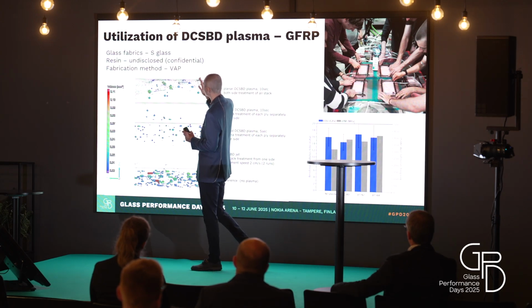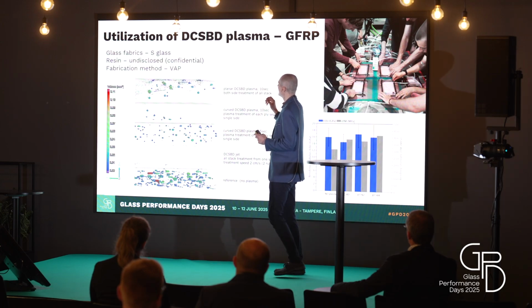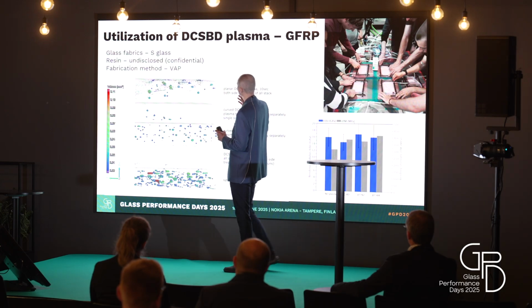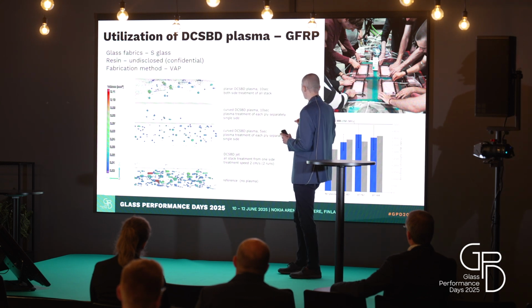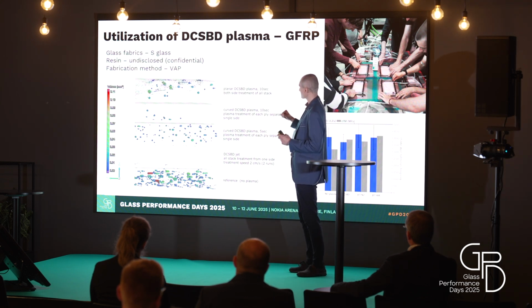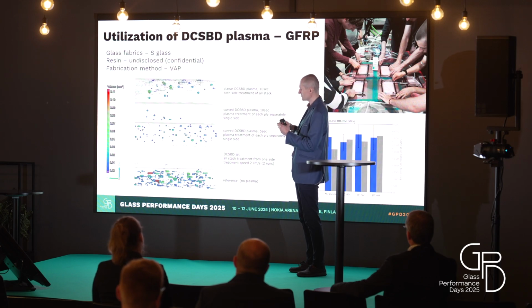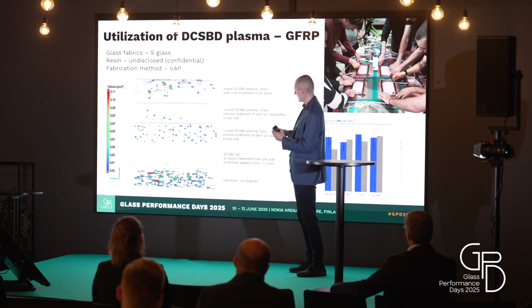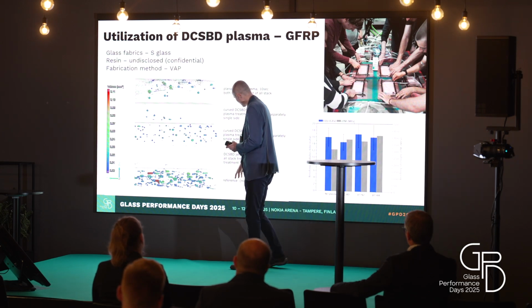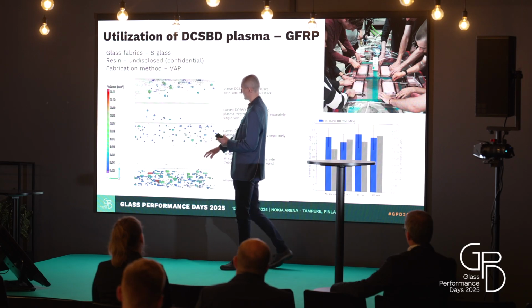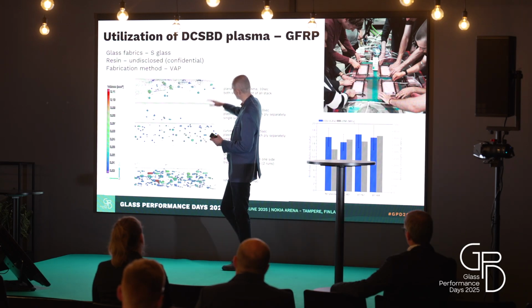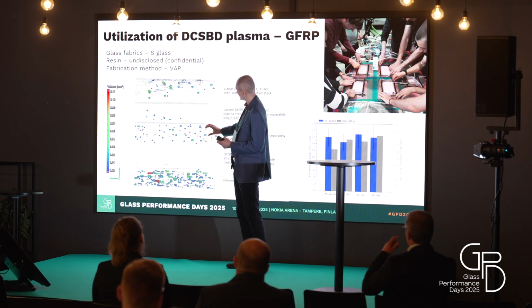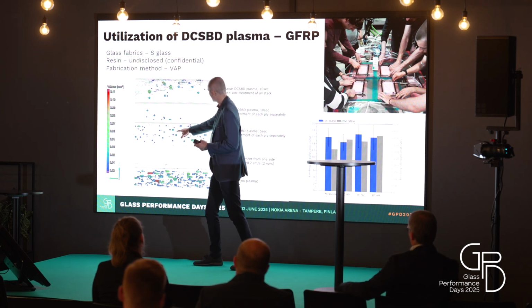Unfortunately, I can't talk about this now. Maybe in person we can talk more. We used a vacuum-assisted method for fabrication of the composite materials, and we analyzed by micro-CT the uniformity of the bulk composite material, and visualized the number and size of the voids in the composite material. In the case of the reference sample, we observed a lot of defects in the material. But when we treated the samples by plasma, you can see that there is a smaller number of these voids, visualized by these balls.